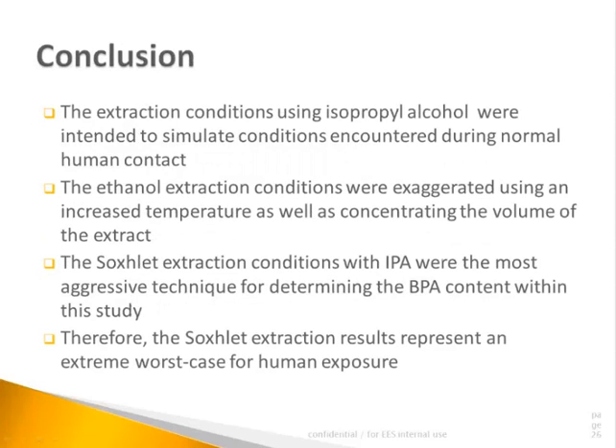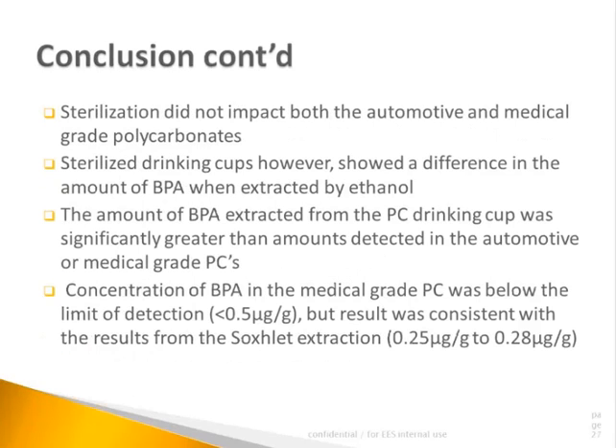In conclusion, the IPA extraction condition was designed to simulate condition encountered during normal human contact. The ethanol extraction was quite aggressive, using increased temperatures of 50 Celsius versus 37 for the IPA extraction, as well as concentrating the volume of the extract. But the exhaustive extraction by Soxhlet was the most aggressive condition within the study. The results from the leaching could be described as the most extreme worst case of human exposure. Next slide.